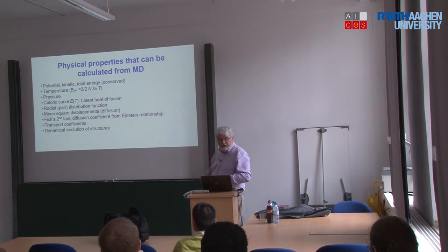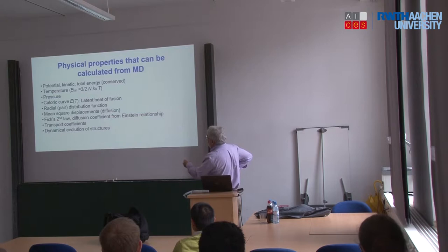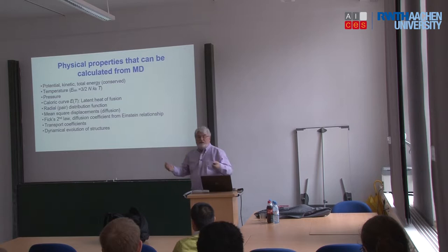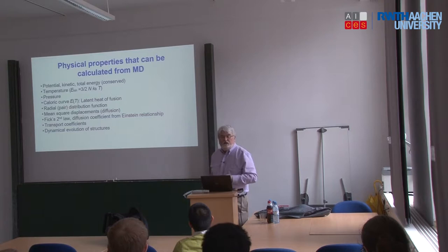Okay. So there's lots of things we can calculate: potential energy, kinetic energy, we can calculate temperature, pressure. We can look at heating curves, radial distribution functions, diffusion, transport coefficients, and the dynamical evolution of structures. All sorts of things we can determine from a molecular dynamics simulation. Now, you're not going to do that for every case because you're probably going to be looking at one of these things. And this should be a dot, dot, dot here. There's many other things you can look at as well. But you'll be picking one of these things that you're particularly interested in for your particular application.